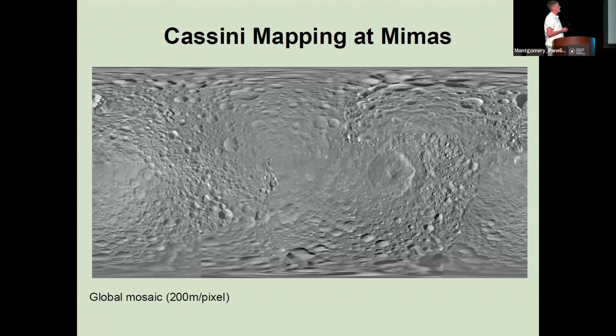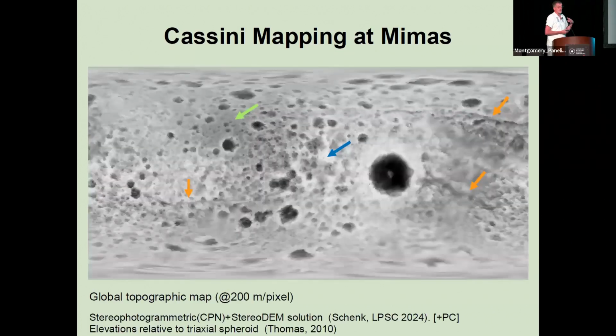And so the result is a global mosaic like this at about 200 meters per pixel, and with concurrent stereo, which allows us to do a shape model. And this is a shape model derived from stereophotogrammetric analysis, which is control point network, and stereo DEM analysis with an additional layer thrown in for photoclinometry, which means that the elevations are tied to the, and in this case, shown relative to the triaxial ellipsoid. This is a true shape model for Mimas, and we have those for all the other satellites as well now.